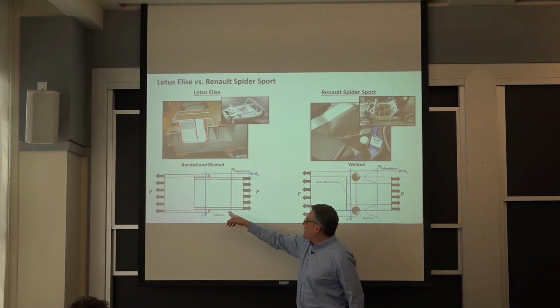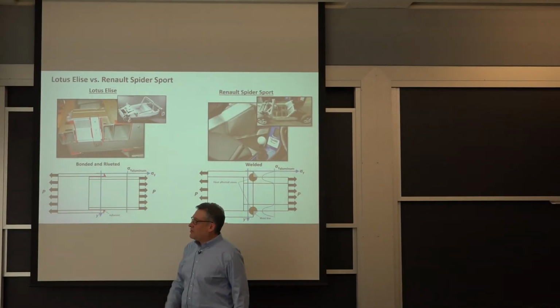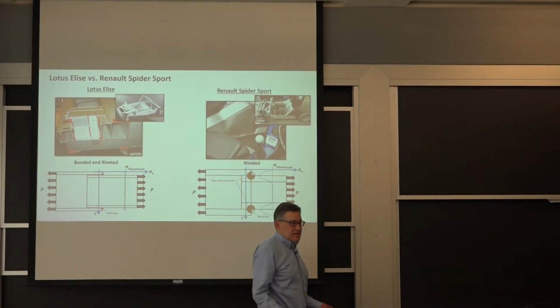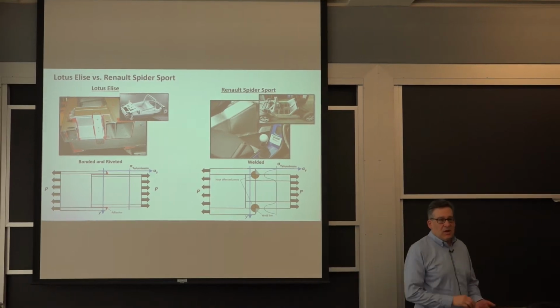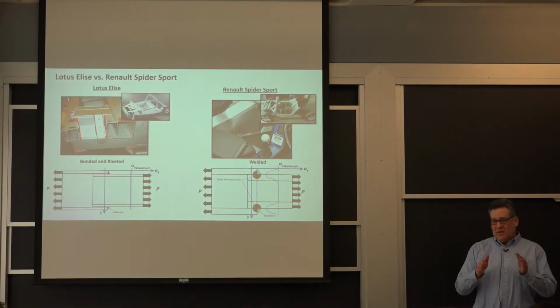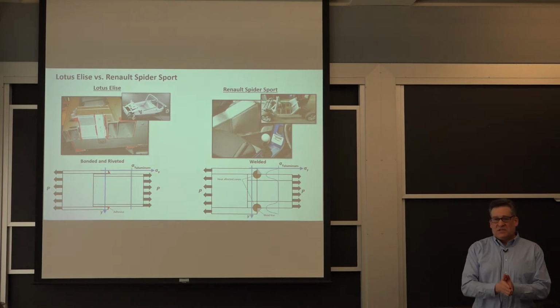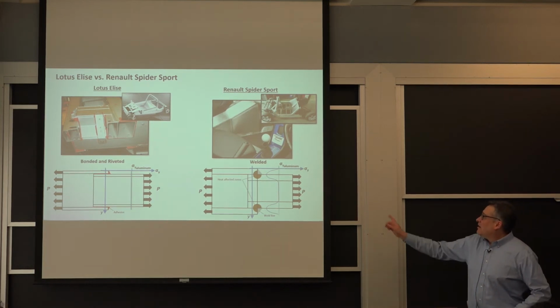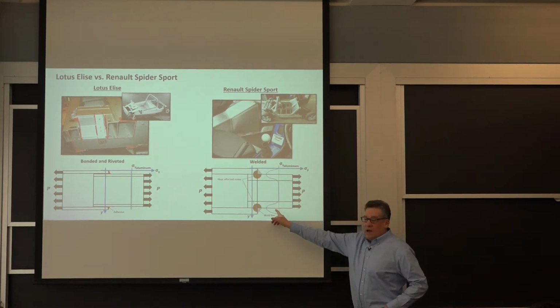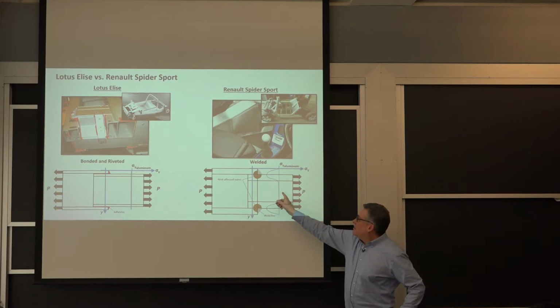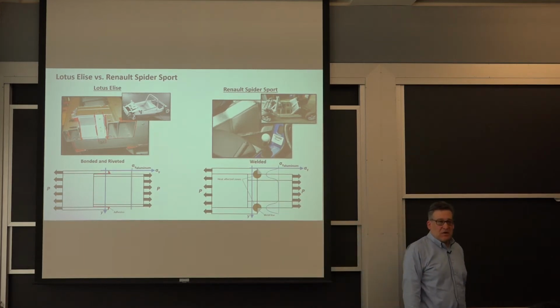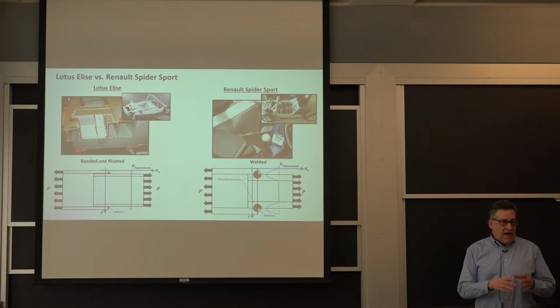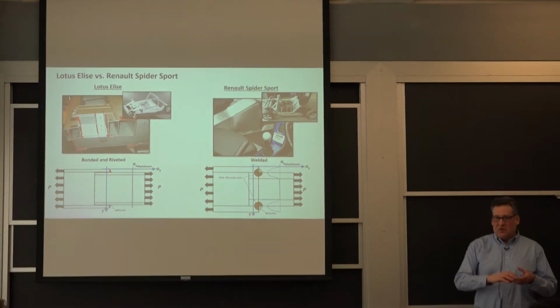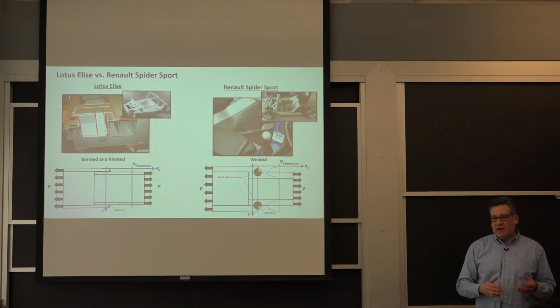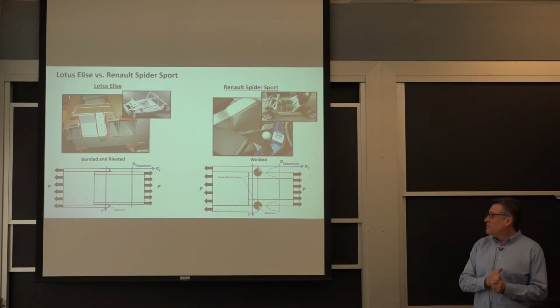If you were to plot stress across this material, the strength of the material stays constant because it hasn't changed. There was no welding, there was no heat cycle. The strength of the material is just as it was as it left the extrusion facility. However, when you weld two tubes together, you get weakening of the material in what's called the heat affected zone. The area that got hot, when it cools, doesn't really cool to the optimal microstructure you wanted, and a lot of times it's softer than the material around it.